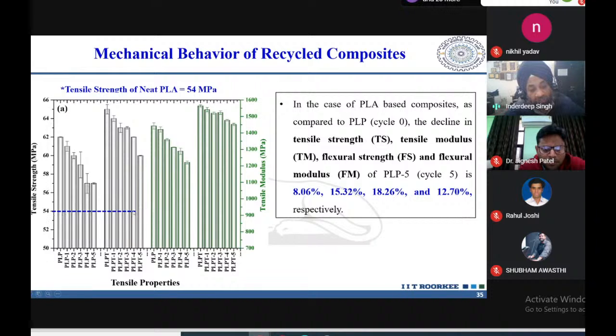So 54 is the tensile strength of the neat sample, but if we integrate fibers into this, we can get tensile strength much higher, as well as the tensile modulus much higher than what we get for the neat polylactic acid. So the first conclusion that can be drawn from here is that if we add fibers into the polylactic acid polymer, we will be able to improve the tensile strength. So here you see this is the fiber, and here you see the improvement in the tensile strength.